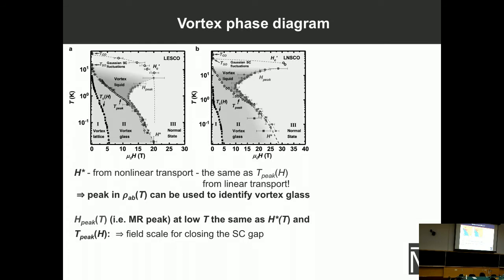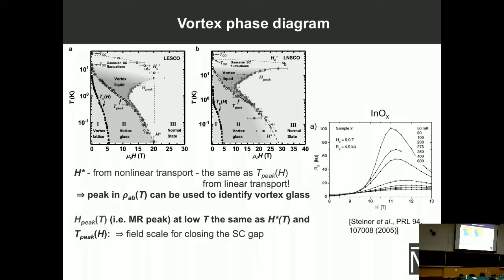So coming back to these phase diagrams, I'd like to emphasize the agreement between our results obtained from nonlinear transport and from linear transport, and in particular, all these different data agree at lowest temperatures, including the position of this magnetoresistance peak. So this tells us that this magnetoresistance peak is the field scale for the closing of the superconducting gap. And this is very similar to what people have found in 2D films of conventional superconductors, such as indium oxide. This has been the subject of a lot of work over many years. And I think the conclusion that has been reached is basically the same as here, that this peak corresponds to the field scale where the superconducting gap closes.